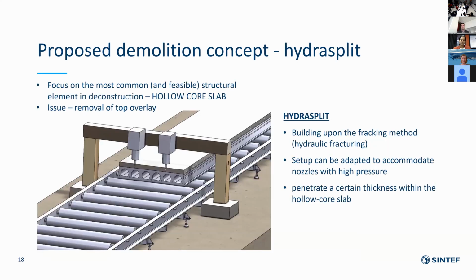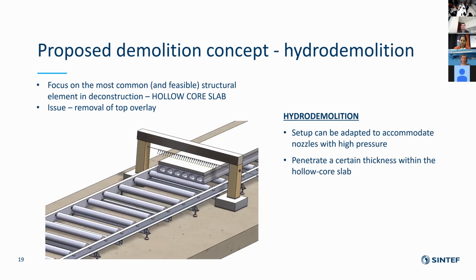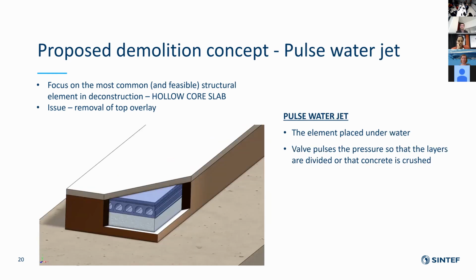We came up with three methods. First is the Hydra split, which is developed upon the fracking method. Here we have some nozzles that penetrate a certain thickness. As I mentioned, the top overlay is up to 5 centimeters thick, so it can penetrate this thickness within the hollow core slab. Then we have hydrodemolition. Here we have nozzles with high water pressure that can remove the top layer. And finally, the pulse water jet. Here the whole element is placed underwater, and a valve pulses the pressure so that the layers are divided or the concrete is crushed.